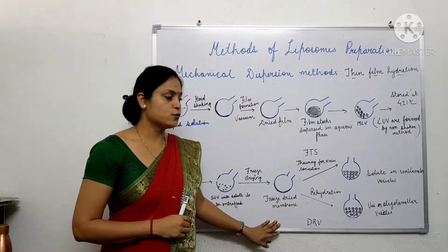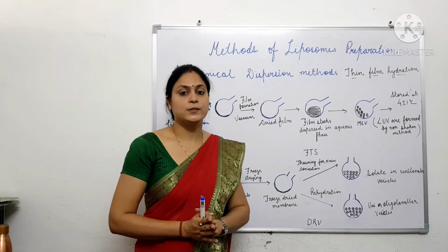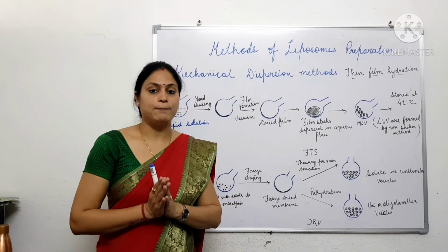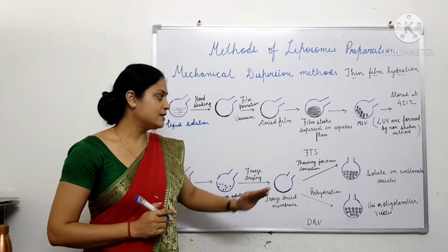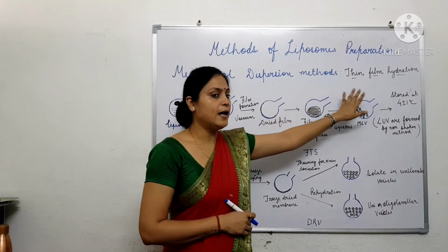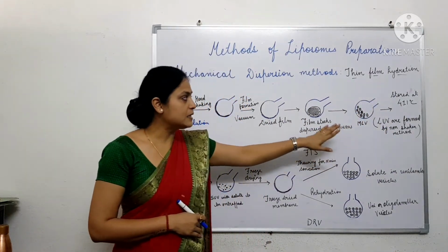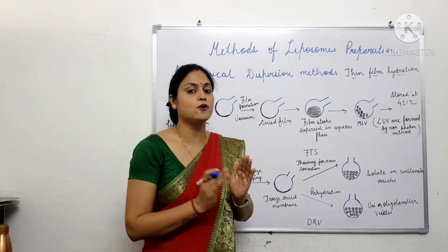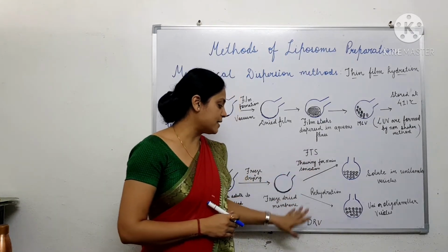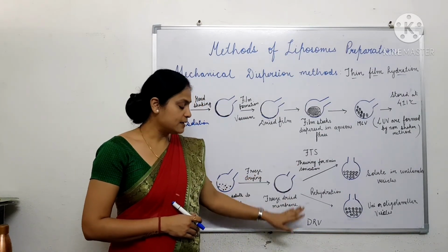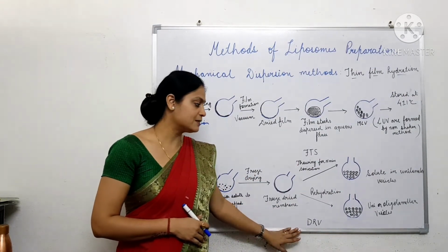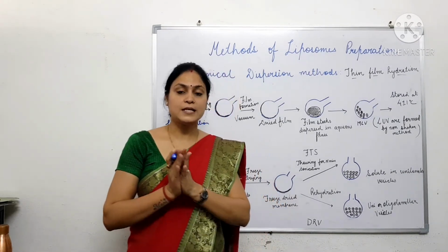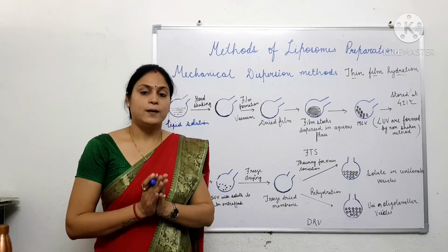But in these liposomes, the entrapment efficiency is as much as 40%. It is increased as compared to the thin film hydration technique, because in the thin film hydration technique, only 10 to 15% of hydrophilic drug is incorporated, whereas in both these techniques, the freeze-thaw sonication method and the dehydration-rehydration method, the entrapment efficiency of hydrophilic drug is increased to as high as 40%.